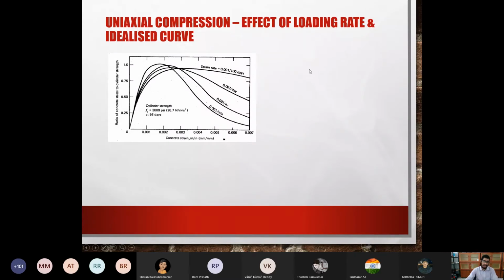Another thing you're looking at is the loading rate. As you see, if you keep increasing the rate of loading, you have a difference in your strain as it goes over time. Of course, the maximum stress will not be much different. This is the ratio of concrete stress to the strength. If you load it really fast, you get a high strength, but it comes down soon. If you load it really slow, look at this rate, 0.001 strain per 100 days, such a slow loading rate, you see that your strength will be slightly lesser, but it does not come down very soon.